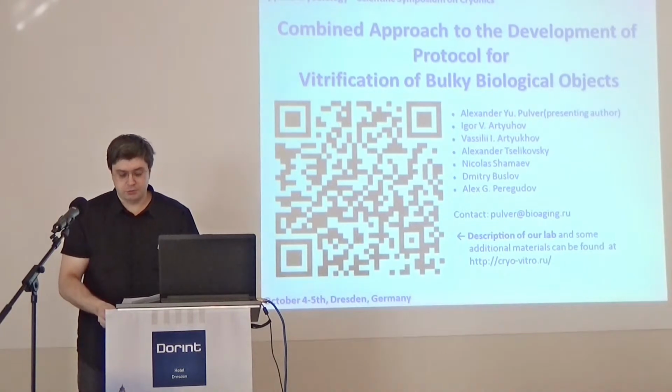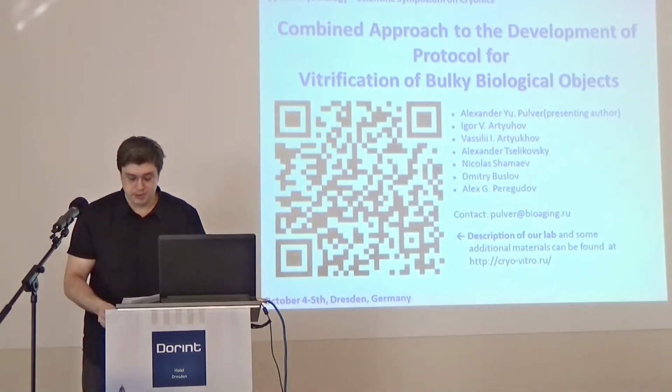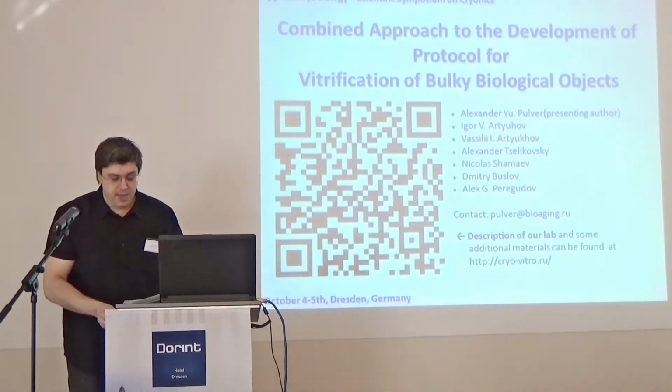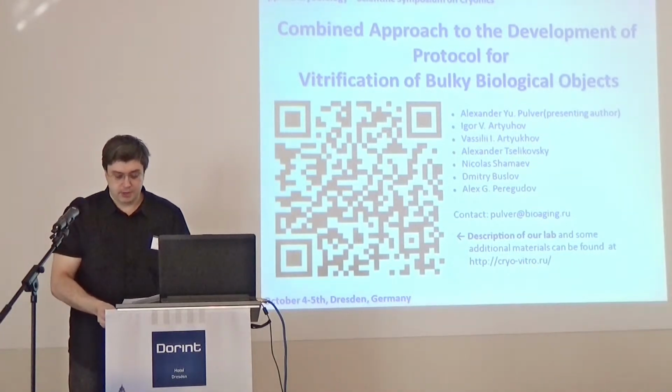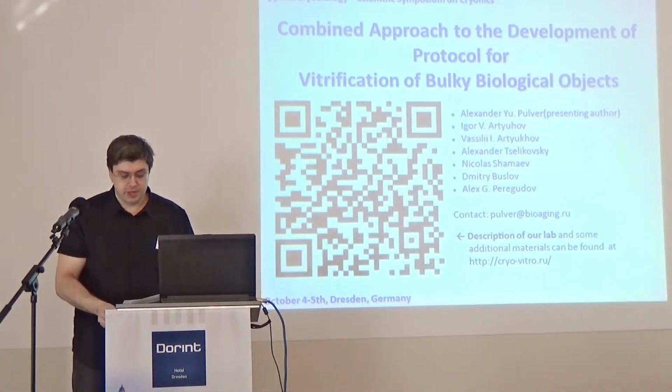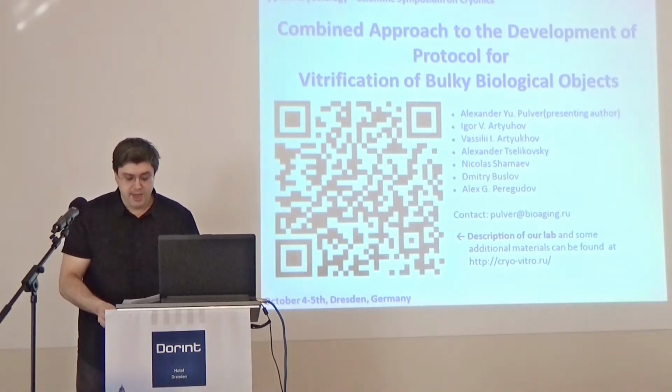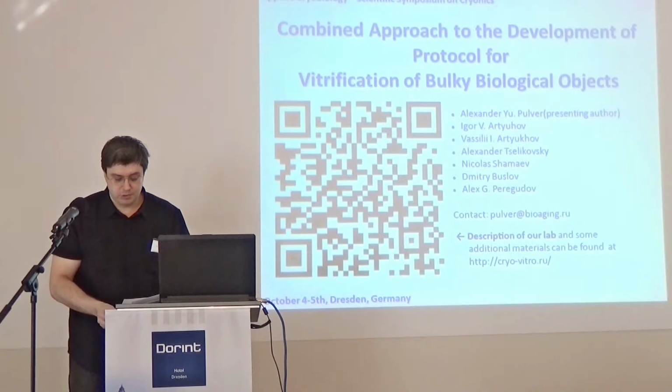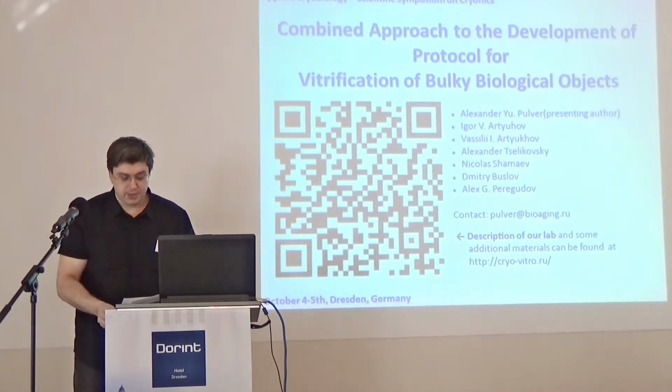Vitrification is a process whereby fluid becomes a solid during cooling. More precisely, it exhibits most of the properties of solids, without any substantial change in molecular arrangement or thermodynamic state variables. Hence, no crystallization with a consequent heat release and volume increase.